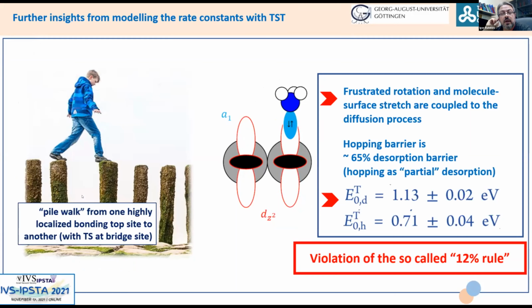So again, now we're getting really the desorption barrier and hopping barrier, and not only an activation energy, because if we are doing this purely in an Arrhenius form, then we actually have a free energy of activation, which also includes entropic influence. Here we are able to disentangle the energetic and entropic influence by applying transition state theory, but qualitatively and so quantitatively, the main take-home message remains the same.